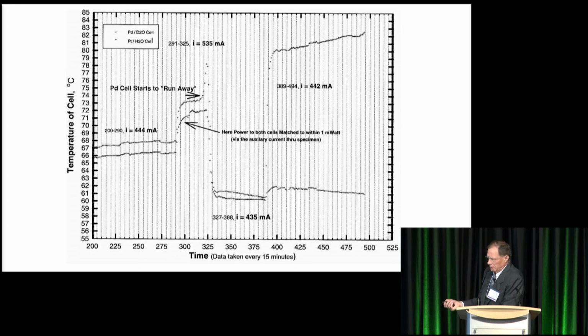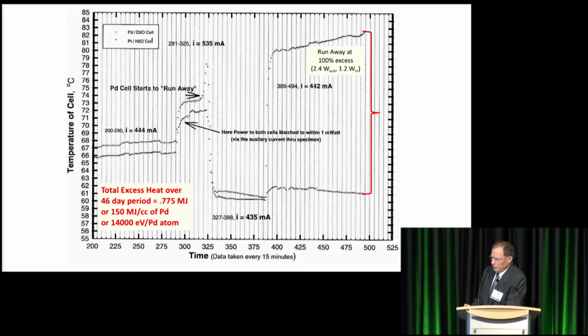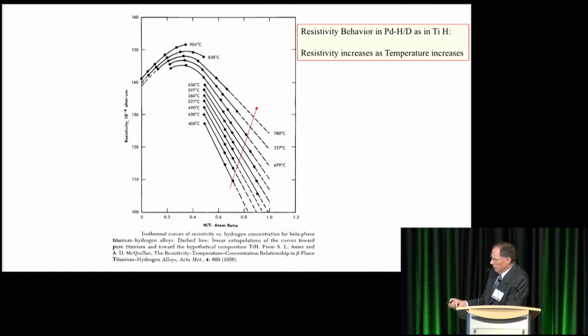And after a little while, I said, well, what would happen if I put it back to where it was at 440? So I turned it back to 442, and it went into another runaway mode, wherein the excess power was double what the input was. So for 2.4 watts out, I was only putting 1.2 watts in. The total excess heat for the 46-day period is 0.775 megajoules, or 150 megajoules per cc of palladium. That calculates out to 14,000 electron volts per atom. So that number is high because the specimen was so small.